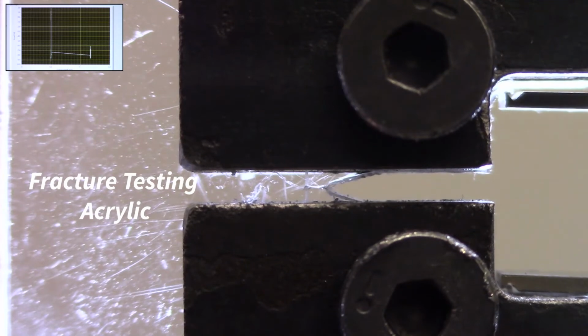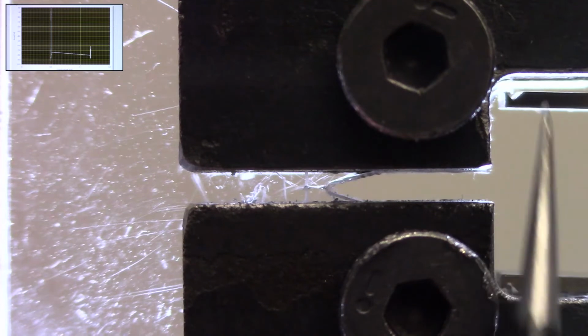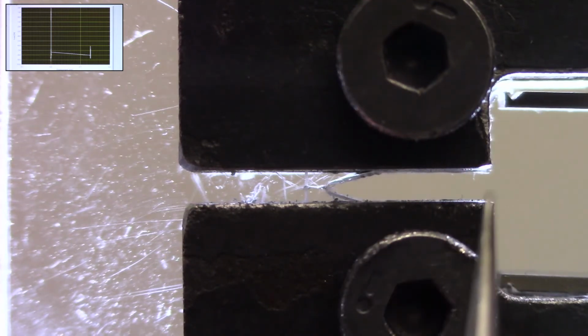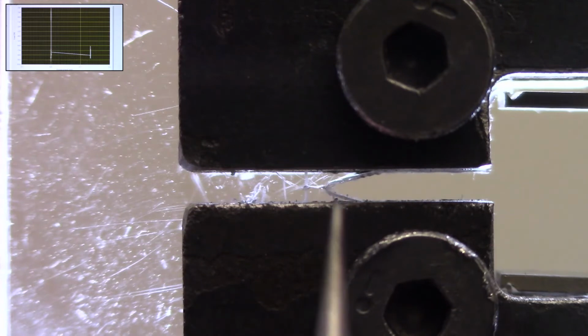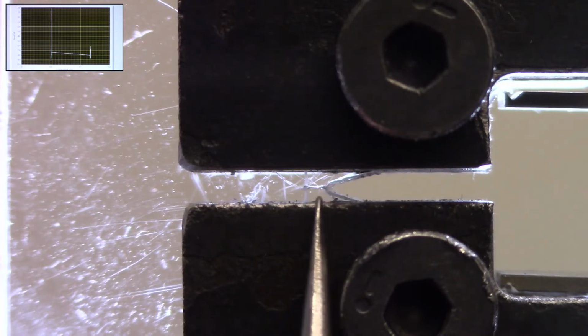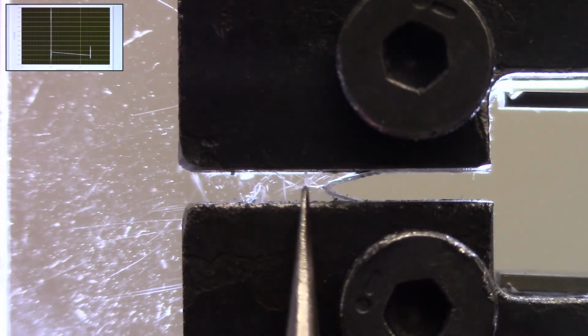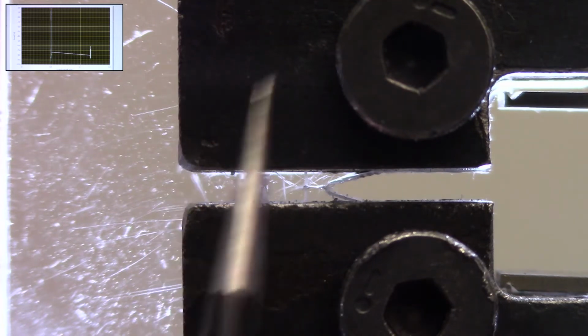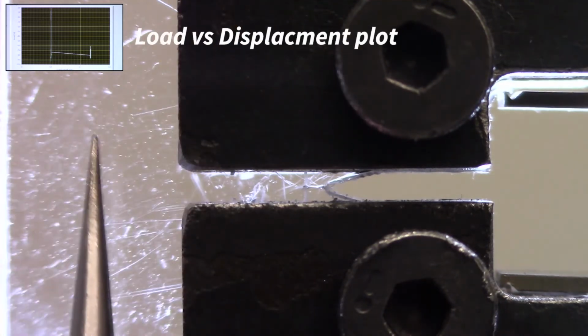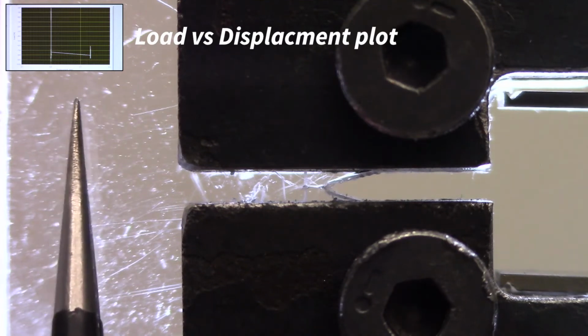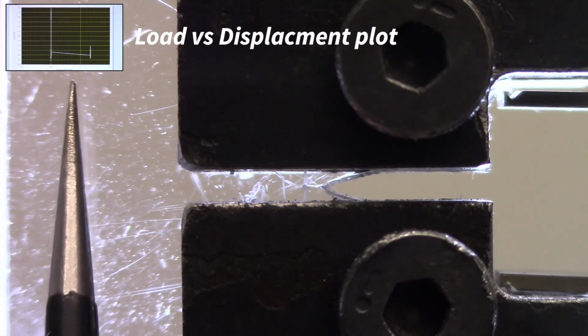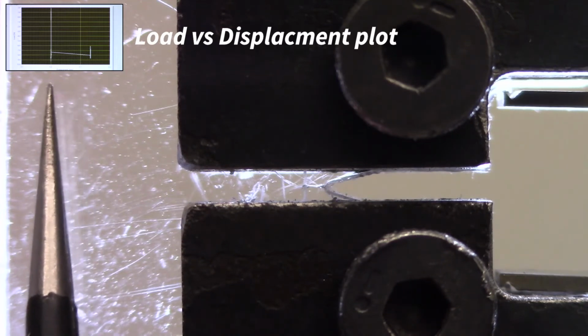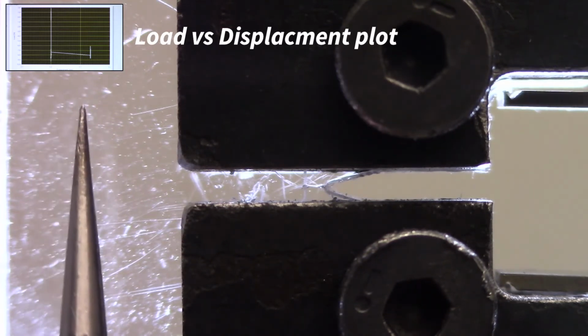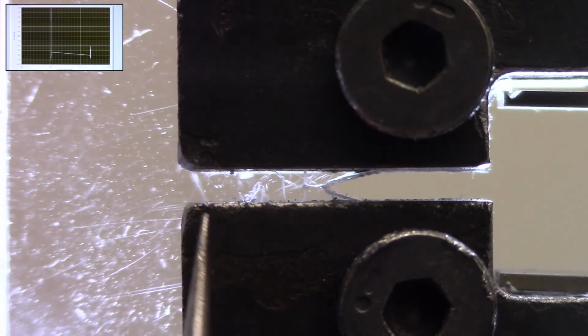Okay, we've got our acrylic specimen loaded into the grips. You can see our clip gauge arms here mounted to the specimen. We've got our starter notch, and at the end of the starter notch we have a small pre-crack, a couple millimeters long, and there's a vertical line marking the end of that pre-crack. Up in the upper left corner we have the workspace from our data acquisition system, and we're going to be plotting load on the y-axis in newtons and displacement on the x-axis in millimeters as measured from the clip gauge.